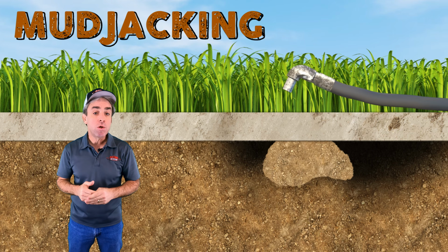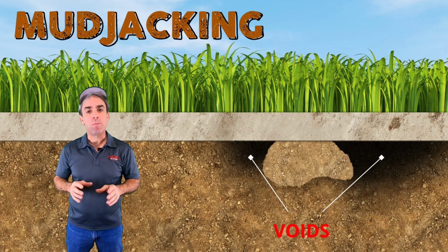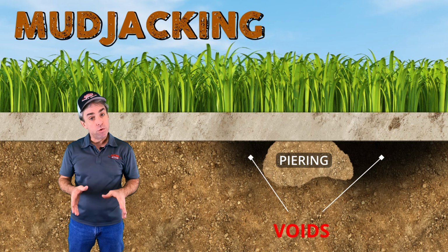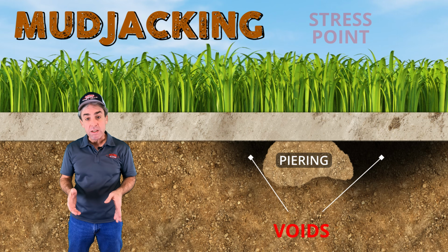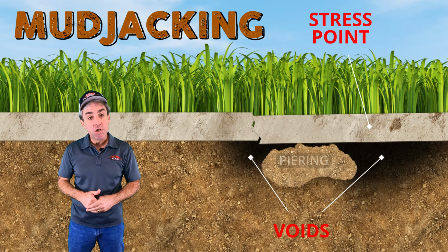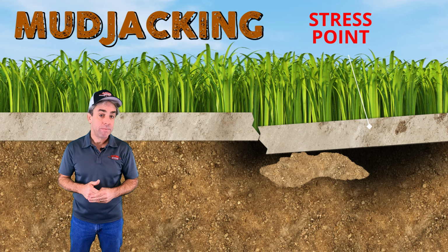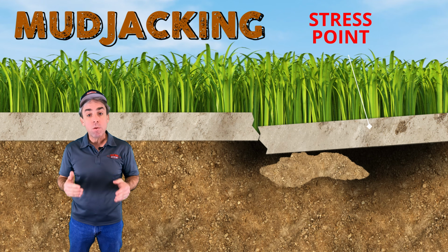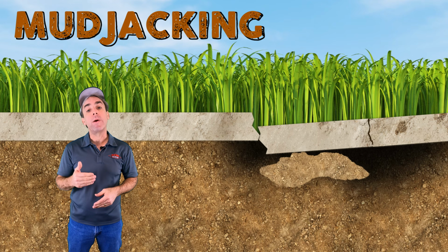Unfortunately, its lack of spread results in voids. We refer to this as piering. The concrete is raised, but the lack of support can leave the slab stressed. Over time, moisture can soften the mudjacking material, resulting in the slab dropping again. What's even worse is that the lack of support can actually result in the slab cracking and require replacement at this point.